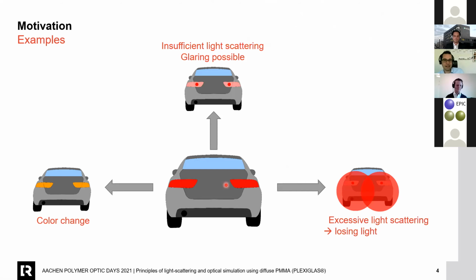If you do the engineering wrong, you can get a color change, for example, because volume scattering is a function of the wavelength of the incoming light. If you use a material with too low scattering, you can get insufficient light scattering, so you can glare the traffic behind you. And if you try to avoid that, you can use very high scattering plastic. You will get excessive light scattering, but you will lose light and the efficiency of your system goes down dramatically.